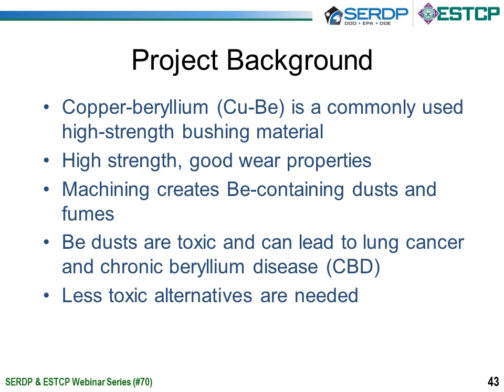The downside is that exposure to beryllium results in a range of diseases: lung cancer, chronic beryllium disease. And the issue is that DoD employees, as other employees, can be exposed to beryllium dust and fumes as a result of the wearing of beryllium-containing alloys during operation, and also during the machining and other fabrication operations. Within the DoD, too, the manufacturing process for copper beryllium bushings results in a large amount of hazardous waste being generated. So we're looking for less toxic alternatives. And the nanostructured cobalt alloy that's the subject of this proposal, we believe, can meet and exceed these requirements.